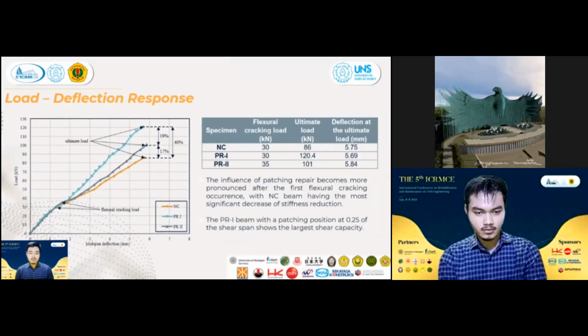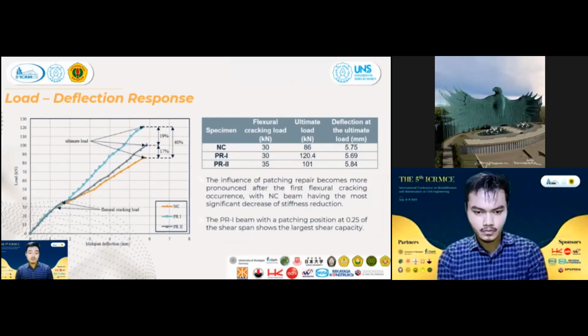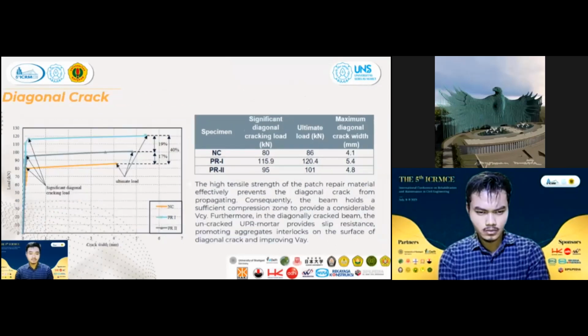The influence of patching repair becomes more pronounced after the first flexural cracking occurs, with NC beam having the most significant decrease of stiffness. The PR1 beam with a patching position at 0.25 of the shear span shows the largest shear capacity, 40% higher than the control beam. And next, diagonal crack.